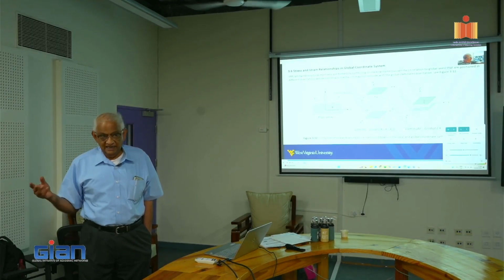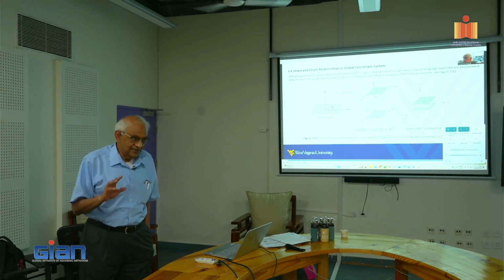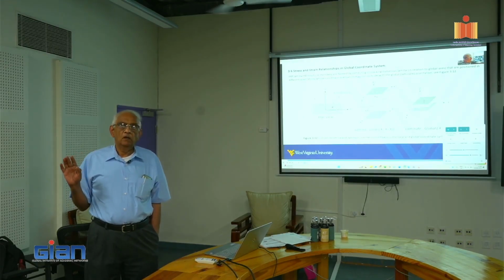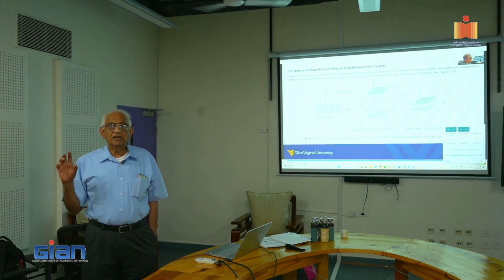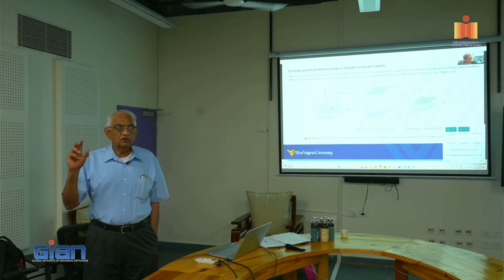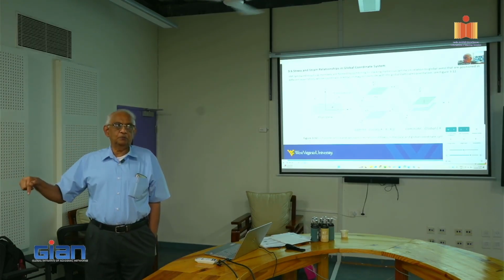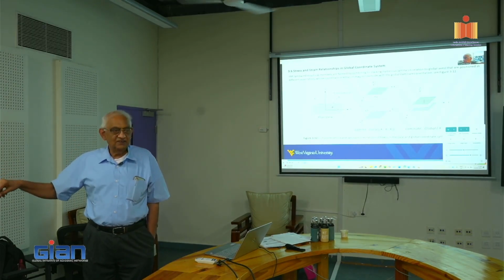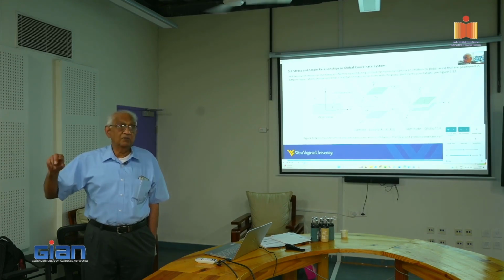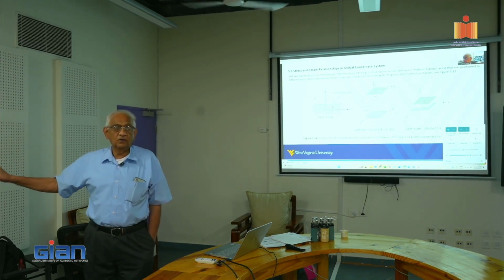Have you used DMTA, the dynamic mechanical thermal analyzer? That will also tell you where the curing problems are, if any. So again, the dynamic mechanical thermal analyzer is a torsional system. Why do they do that? It's easy to figure out from the shear response point of view what the stiffness is compared to the tension compression response point of view, because that is driven by the shear strength, which is the least value in terms of the resin, unlike the fiber.